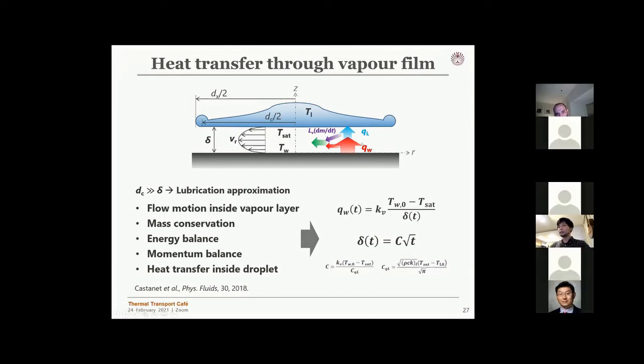We have a heat balance equation considering this. Also, since the vapor layer should be much thinner than the droplet size, we can apply lubrication theory to model the flow motion inside the vapor layer. We assume Poiseuille flow, mass conservation, heat balance as explained, and momentum balance. We have to calculate the pressure in the vapor film such that it can keep lifting the droplet. Also, heat transfer inside the droplet should be calculated.